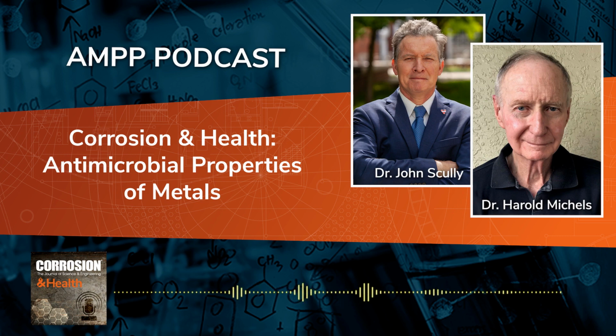The whole idea of how things work and how do you use them is absolutely critical. We did a lot of laboratory work on copper alloys, but we finally said we have to do a clinical trial. And we did a small clinical trial at North Shore University Hospital on an outpatient phlebotomy chair, which is basically taking blood samples. It was an infectious disease clinic. And we put in just the top of the where the arm rested when they were taking the blood sample. And we found that there was less bacteria present on that versus the wood surface that's coated with a laminate of plastic, and that was highly contaminated.